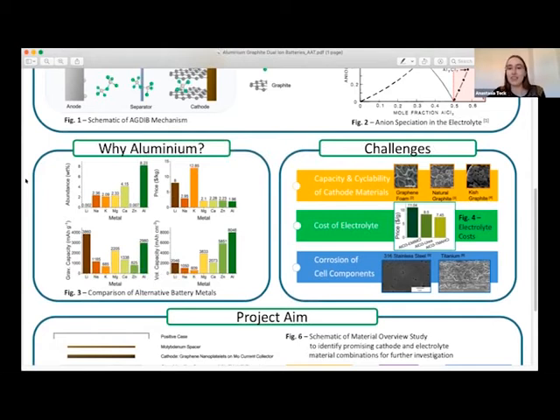Third, the ionic liquid electrolyte used is strongly acidic and very corrosive to some of the cell components, so that the stabilities of, for example, the current collector and cell casing are a challenge, showing two examples of corrosion of stainless steel and titanium after potentiodynamic tests in EMIC chloroaluminate electrolyte. So this means that ways to protect cell components or a way to reduce the electrolyte corrosivity are needed.